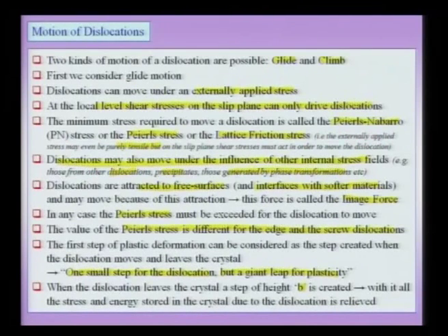But when this dislocation leaves the crystal, it relieves all the stresses associated with it, and it is now only a surface step and can no longer be called a dislocation. So, it ceases to exist as a dislocation, and it leaves its final mark as a small step of height b or width b on the surface. So, this is where we can consider the dislocation to have died or left the crystal.